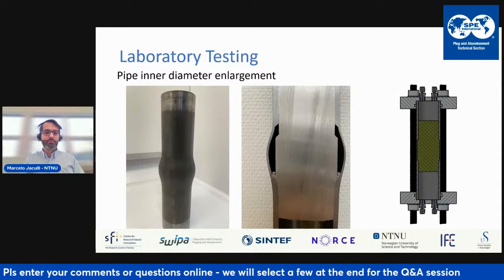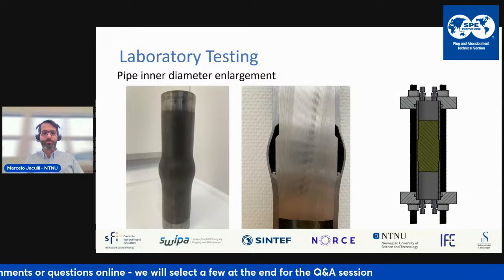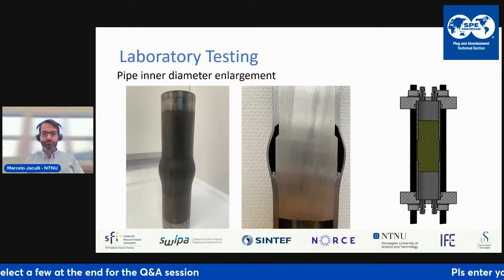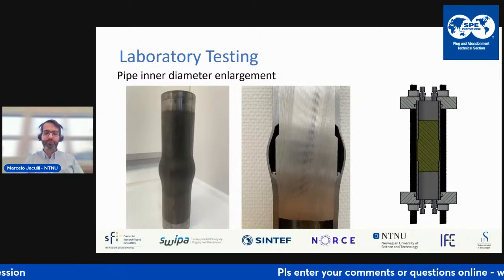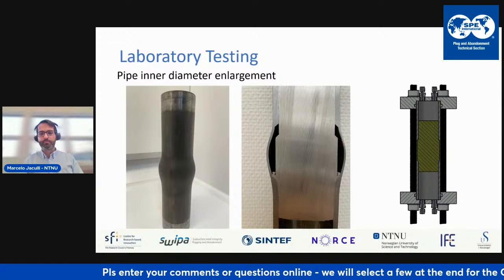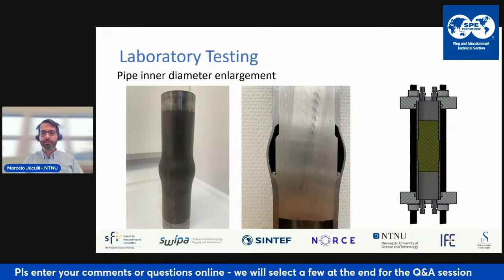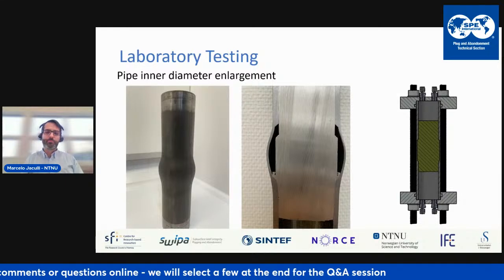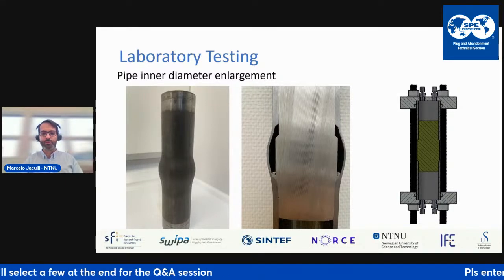Another thing we tried was increasing the pipe inner diameter. You can see in the picture in the middle that we cut a section of the pipe thickness. This increases the inner diameter and creates kind of a seat, as you can see in the diagram on the right, where once the plug solidifies, it improves its contact area with the pipe.